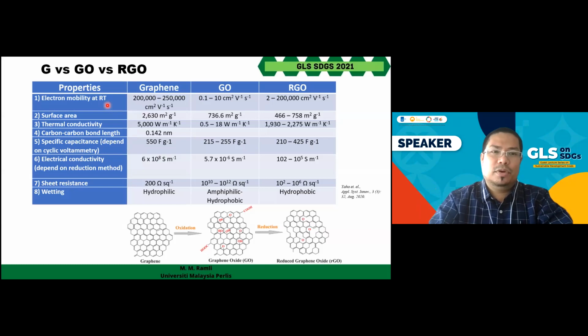So that is very important when you're trying to play around with, or enhance, the properties of your graphene here. It says here that at room temperature, this is the value of the electron mobility. Understandably, when you attach functional groups on the basal plane of your graphene, the electron mobility will drop, because the functional groups disrupt the network conjugation of the C double bond C in the hexagonal lattice of your graphene.